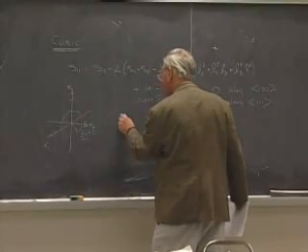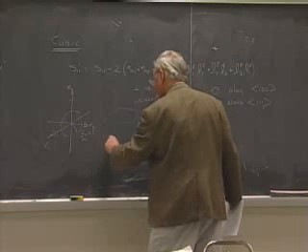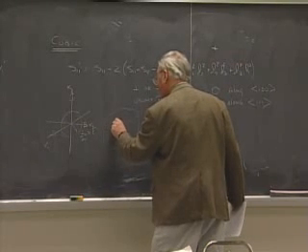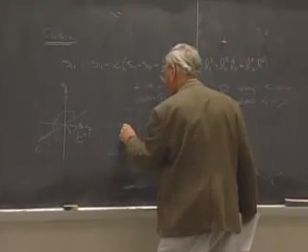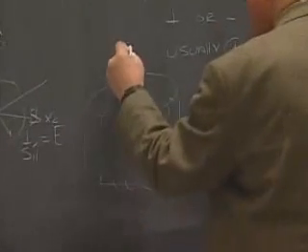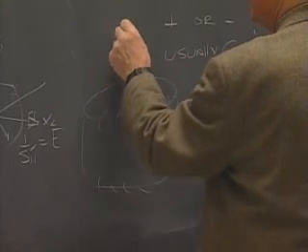And the best way I can describe this surface, it's not a simple surface, it looks like a cube with fuzzy edges. So you had a cube and started to dissolve it. So this is how the reciprocal of Young's modulus varies with direction.